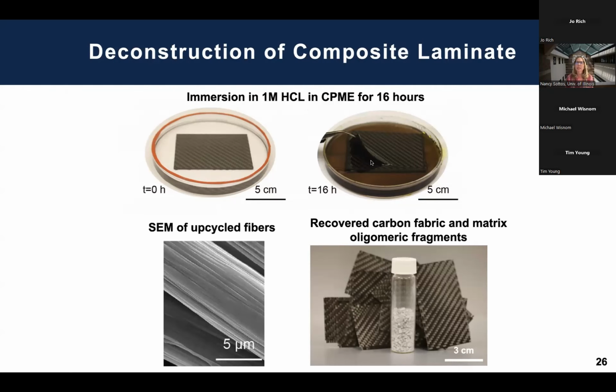And again, I'm not going to show the XPS of the fibers. They're remarkably clean. This is just an SEM to show you that. And we're in the process of doing the characterization on the tensile strength, but actually it's really promising. There's almost no damage to these fibers that we can see. And in fact, they're super clean. They don't have sizing on them anymore, which is also, I think, a benefit.